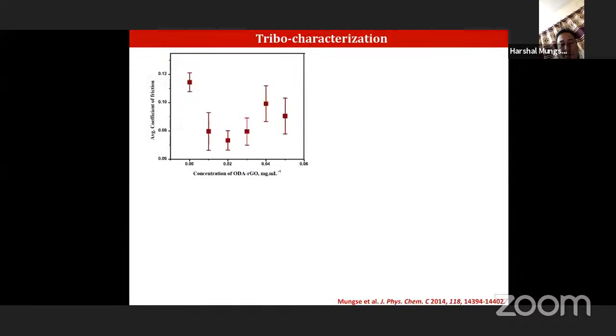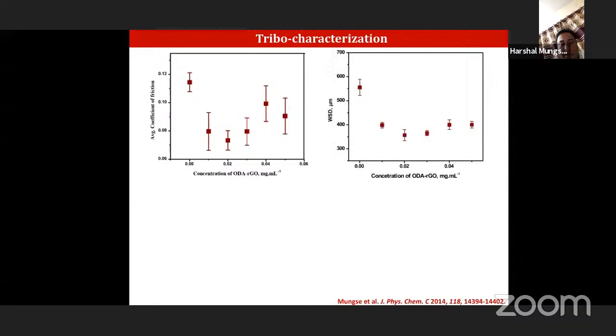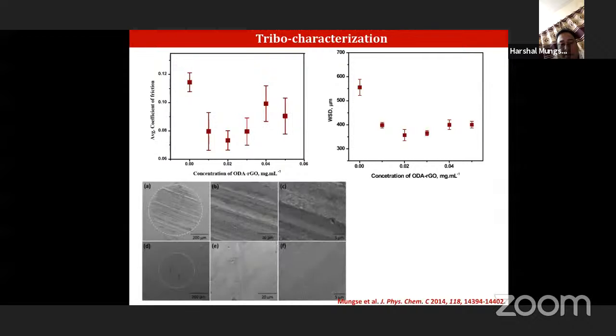Now you can see the tribo characterization. At the 0.02 milligram per ml concentration, we can see how much friction is reduced. There is a significant reduction in the friction at this concentration. This is the optimized concentration. In another case, you can see at 0.02 milligram per ml how much the wear scar diameter is reduced. There is a significant reduction in the wear scar diameter. And these are the images.